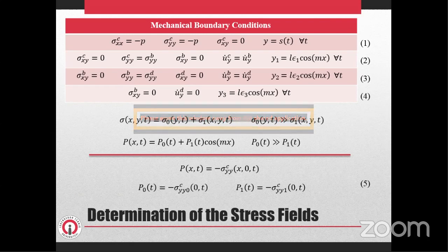Due to the sinusoidal form of the temperature fields and heat flux with added perturbation on them, the thermal stress fields and contact pressure at the shell-coating and coating-mold interfaces may be written in the following forms. The magnitude and direction of the contact pressure at the solid coating layer interface are the same as the y-directional stress field in the solidified shell at y equals 0, but it has a negative sense, which is defined by equation 5.